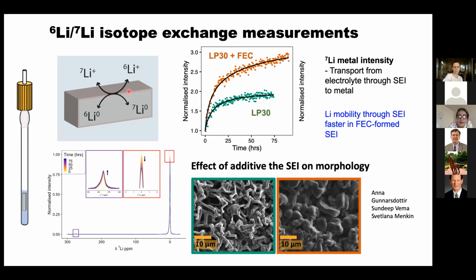And that's something we can then quantify by doing isotope exchange experiments, where we can, for example, look at lithium-6 metal in a lithium-7 electrolyte and actually quantify that effect. So the sort of take-home message from that is, if you make an SEI with better lithium transport, then you can move towards these less dendritic structures and in principle, hopefully get more stable cycling.